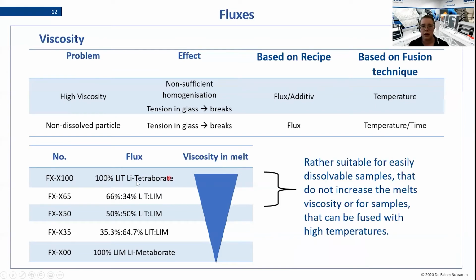What does that mean? The fluxes that contain a higher tetraborate part are rather suitable for easily dissolvable samples, like samples that do not increase the melt's viscosity. But as well, we can have a look at the fusion technique there. When we are able to fuse these kinds of samples with higher temperatures, we might as well use fluxes containing a higher part of lithium tetraborate, even though the sample might not be easily dissolvable.